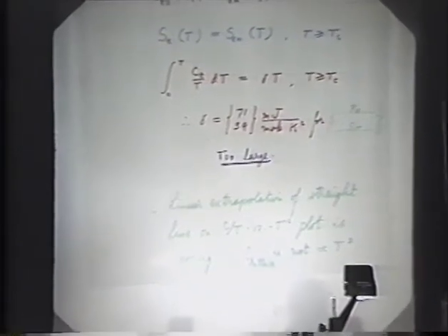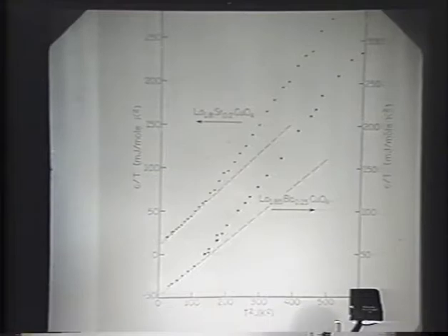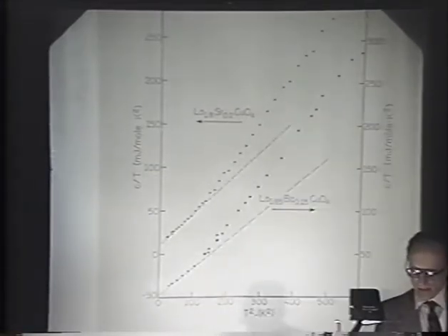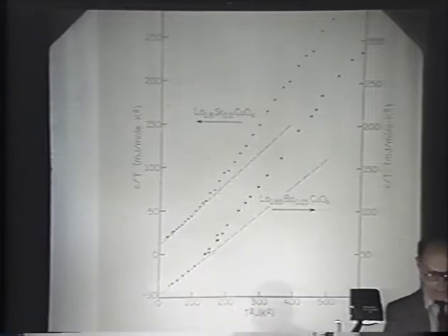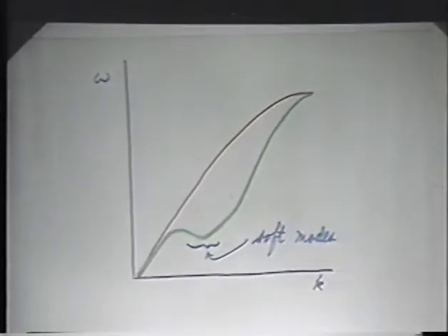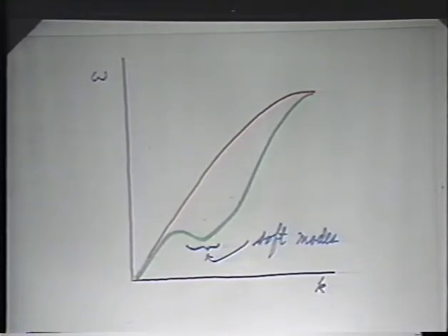So as a result, we conclude that the linear extrapolation indicated on the previous viewgraph was incorrect. In other words, the lattice specific heat does not extrapolate along that straight line. Most of the specific heat you see here at these temperatures, beyond which the plot deviates from the straight line, is phonon specific heat. What that indicates to us is that there are soft modes around, because the Debye model assumes a straight line relation between omega and k, and this excess specific heat that we see in the lattice would correspond to phonon modes of unusually low frequency. And you heard several theorists much earlier in the evening say that they thought there were soft modes in these materials and that they play an important part in explaining the high transition temperatures.